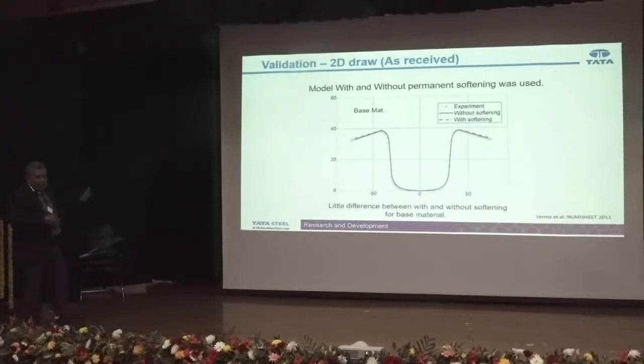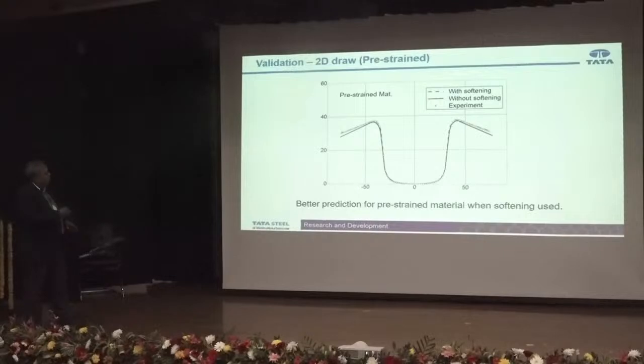And then the simulation was done using the in-house developed material model, and this is for the base metal. You can see for the base metal the prediction is very good. But when we started doing the simulations for the pre-strain, it was actually not working. When we say with softening and without softening, we are talking about two different material models. You can see that with softening it predicts very well, whereas without softening it doesn't predict that well. So we said you need to have advanced material models with softening, etc., to be able to predict the springback more accurately.